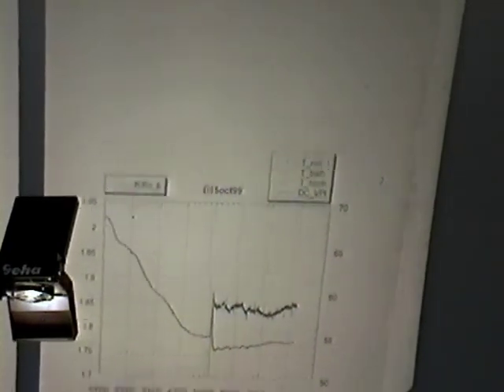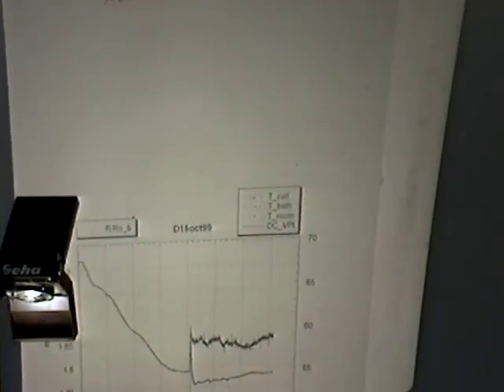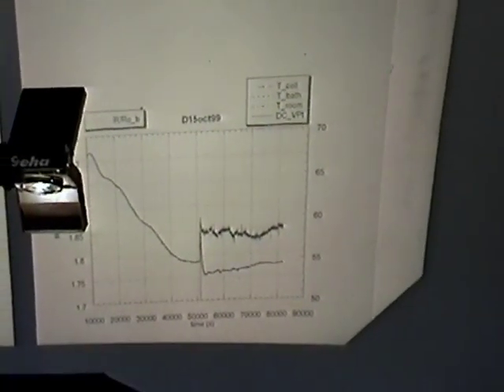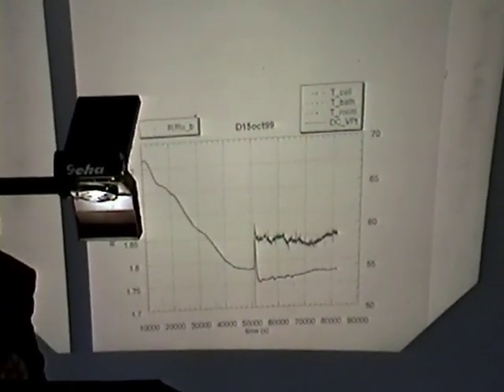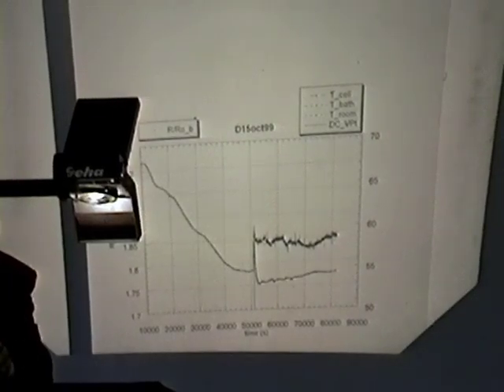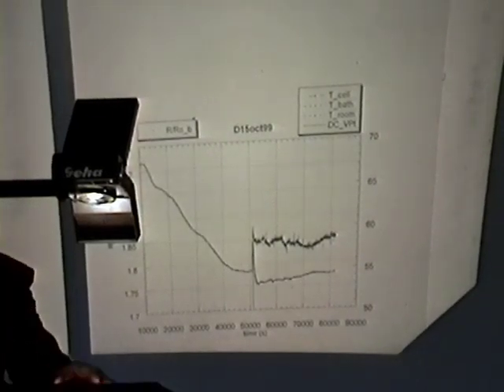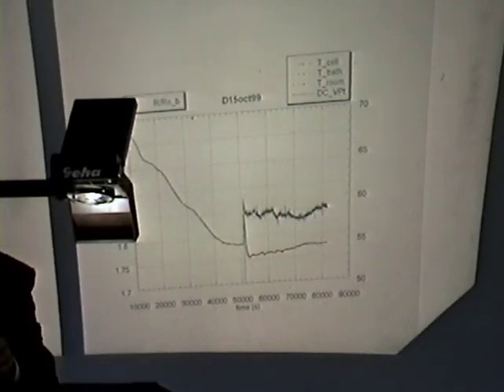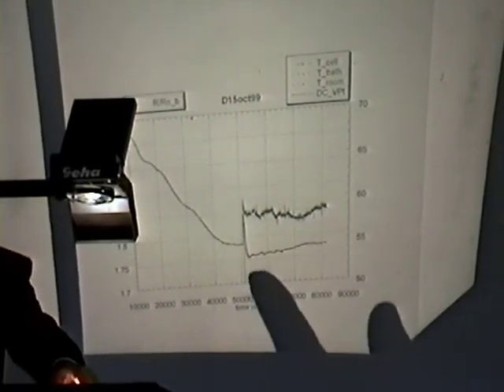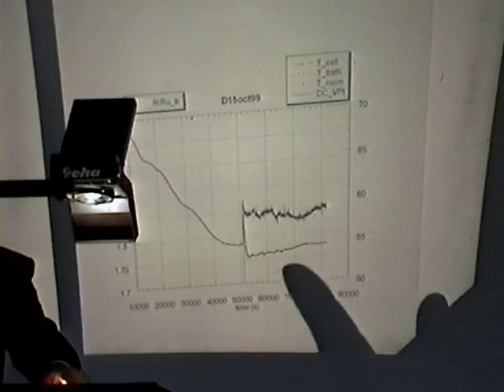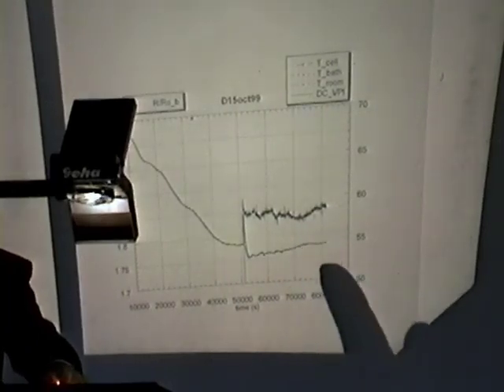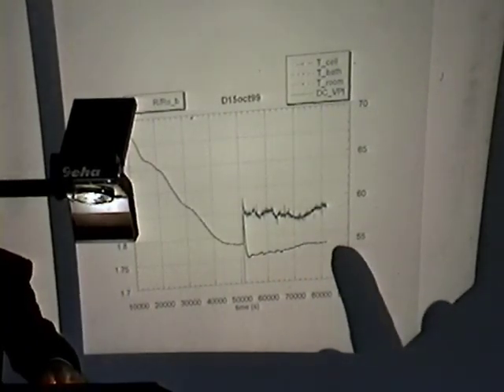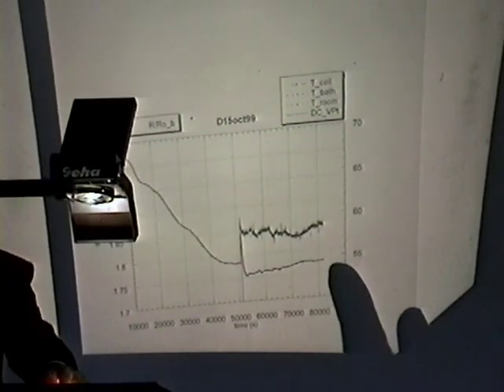We made another experiment using filtered deuterium oxide with 100 nanometer filters, very small size, a Millipore filter in series. We improved the loading, 1.75, but even increasing the current, after that there is no stability. But it means the filter can help. An indication of something.